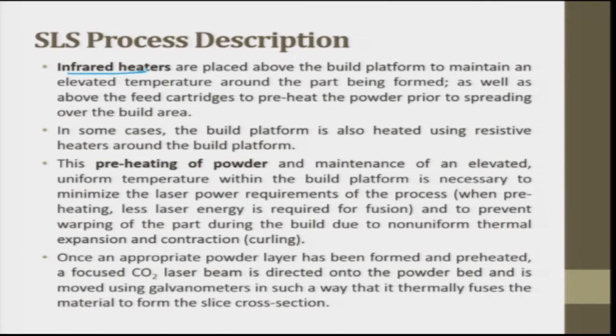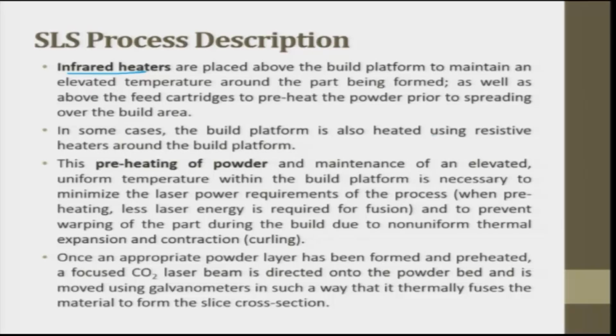Infrared heating: infrared heaters are placed above the build platform to maintain an elevated temperature around the part being formed, as well as above the feed cartridge to preheat the powder prior to spreading over the build area. That's what I said. If there is any moisture, or any untoward polymer slightly mixed in, when you start preheating, it gets gassed away and removed. In some cases the build platform is also heated using a resistive heater. It can be infrared, it can be resistive.